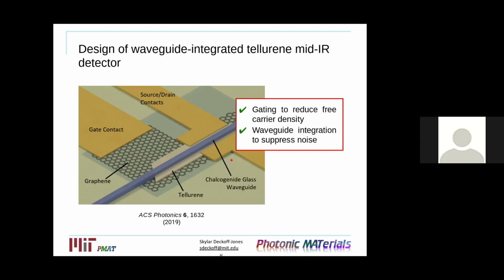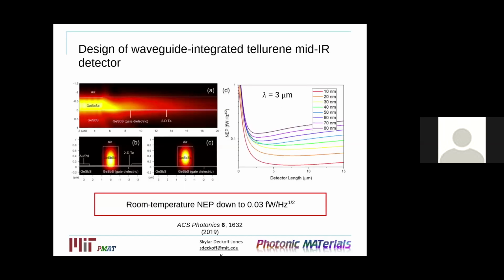However, we were thinking that we can further improve the device performance by also including a graphene gate. So we can have graphene, which can act as a transparent gate material in the mid-infrared, as well as a gate contact, and again, using our chalcogenide glass as a gate dielectric. So this would allow us to control the carrier concentration in the tellurene, which will lead to further improvements in the device performance, which can be illustrated here.